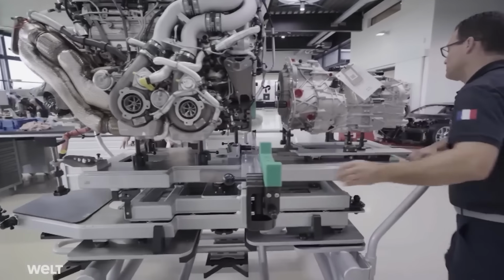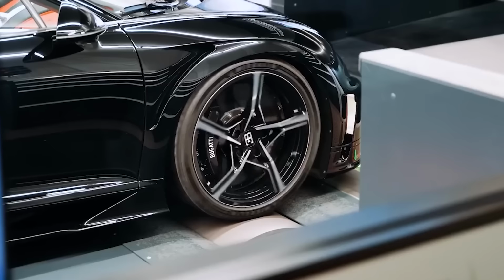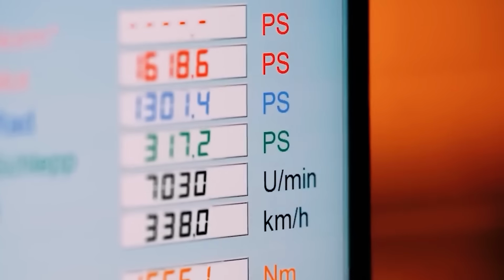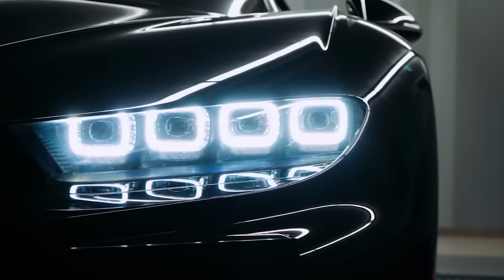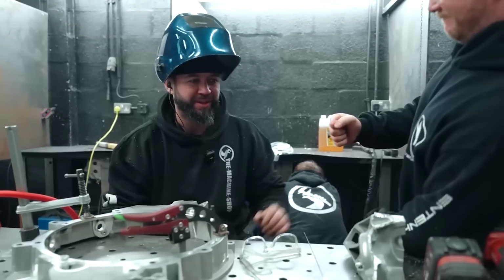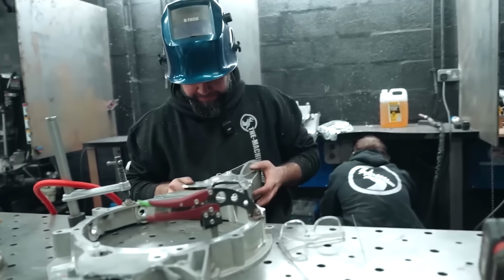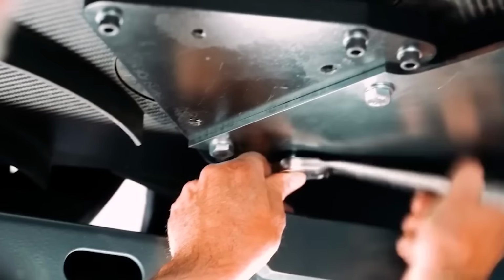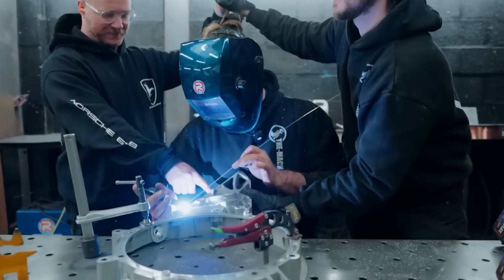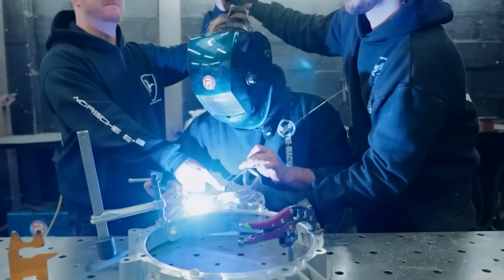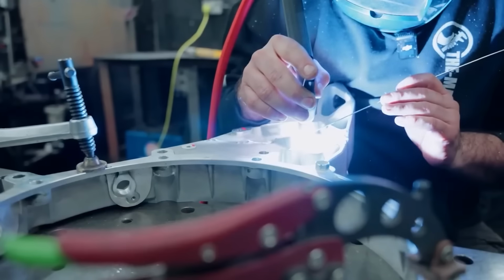Bob sets up the test. He selects 4047 filler rod. It flows more smoothly than the alternative 4043, which matters here because the geometry of the repair will require some gap filling. He's also planning to add reinforcement plates, so the raw strength of the filler rod matters slightly less than its workability. He strikes the arc.